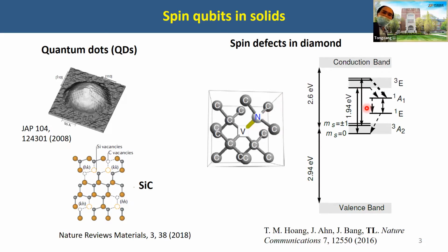And then when we have an NV defect, we create new energy levels in the band gap. So we have a ground state, which is a spin-1 system. That means the electron spin can be 0 or plus or minus 1, and there is an excited state. Then we can shine a laser to excite from the ground state to the excited state, and it will decay. This decay depends on the electron spin. So by shining a green laser, like a 532 nanometer laser, we can polarize the electron spin to the spin 0 state. And we can also read out the electron spin, because the spin 0 state is brighter than the plus or minus 1 state. So this allows us to initialize the spin and read out the spin.